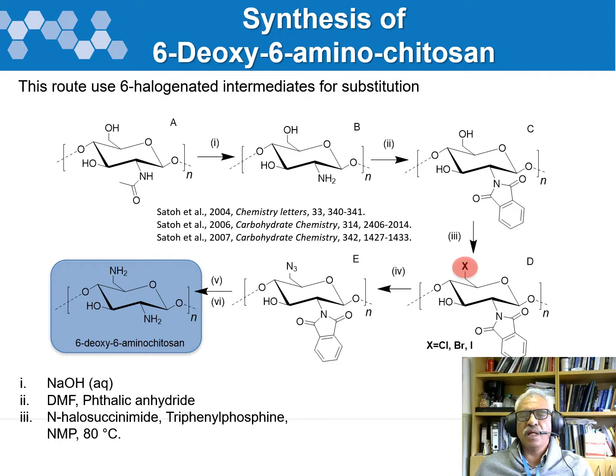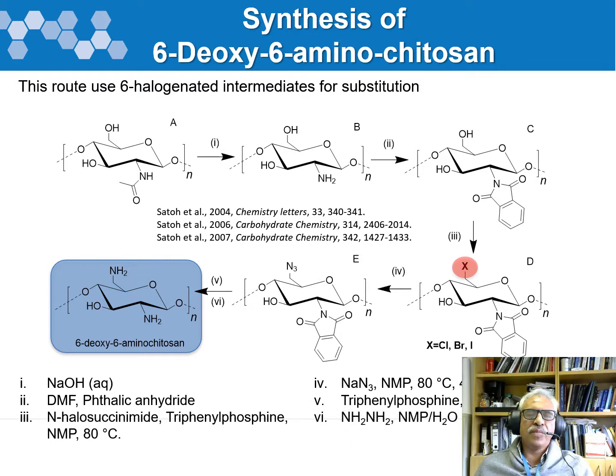This will convert hydroxy to the halo intermediate here, and then you substitute the halogen for an azide, and then you do a Staudinger reduction with triphenylphosphine, and of course after deprotection of the phthaloyl group with hydrazine, you then have the 6-deoxy 6-amino chitosan, which is completely water soluble. However, in our hands, we could not get the solubilities reported because a lot of the product still has lots of triphenylphosphine oxide in there, making it very hydrophobic, and therefore we could not get the solubilities claimed, and obviously we wanted to improve on this process.